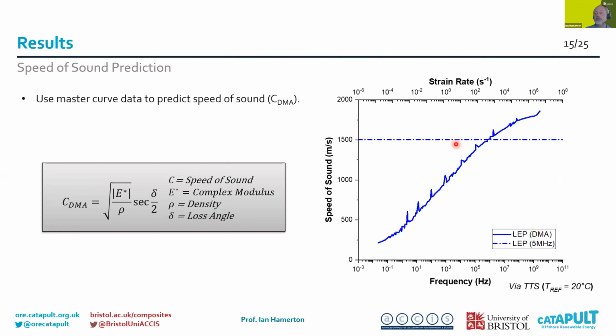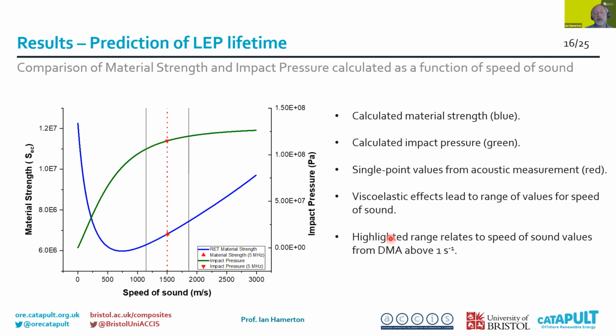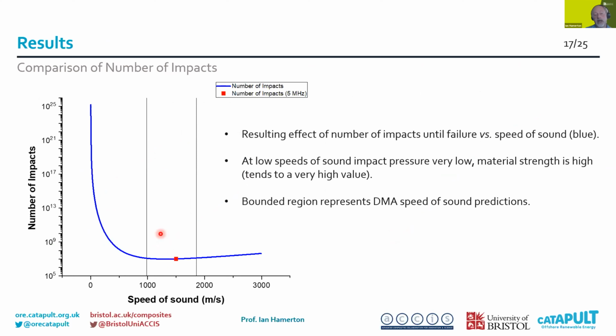It bears little relation to what we see across the whole range of the properties of the material. So what this means for us is, if these values here in red are the single measurement for the NDT data, they bear little relationship to how those data, be it the material strength or the impact pressures, change as you begin to shift the speed of sound. You can see the same for the comparison of the number of impacts. We've got a single value down here, but the DMTA values allow us to extend that over a wider range. So what does that mean for us?